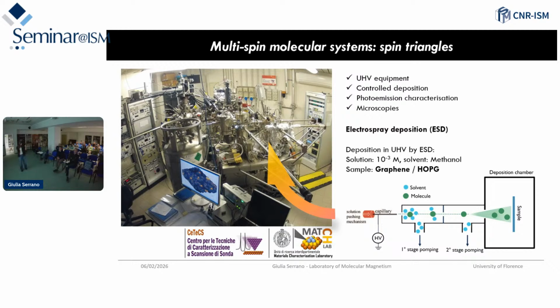The point is that, first of all, you have to use polar solvents. A non-polar solvent wouldn't work because it cannot be polarized by the voltage. So the drop cannot be deformed and cannot spray inside. So you need to use water, but water is not nice, never nice. So methanol or something that is polar, actually. And this could be an issue sometimes in chemistry because the organic ligands are soluble most of the time in a non-polar solvent. But you can use a mixed solution. Okay. But you don't protonate. Thanks a lot. Welcome.